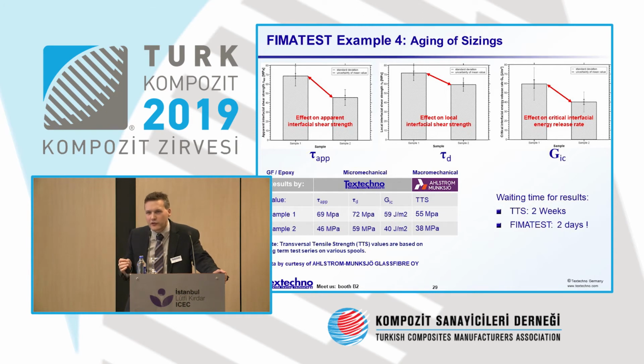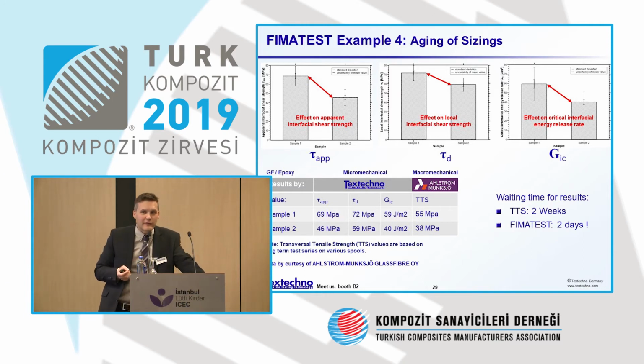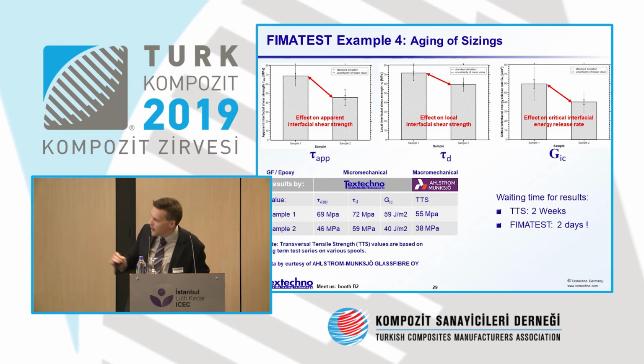And basically we were able to prove the same behavior also with the micromechanical testing. The advantage of the micromechanical test is that the turnover time is about 2 days for this test, whereas the macromechanical testing actually takes them 2 weeks. So it's a huge speed up in testing time until you know if you can really use these fibers inside your production.